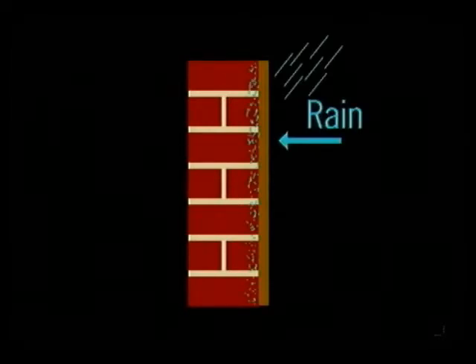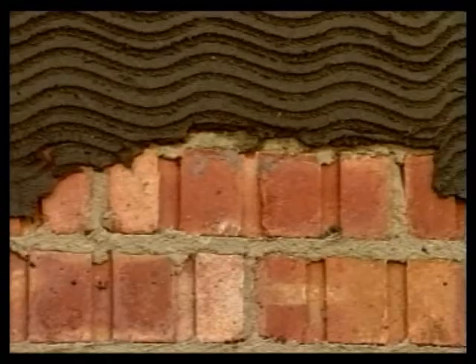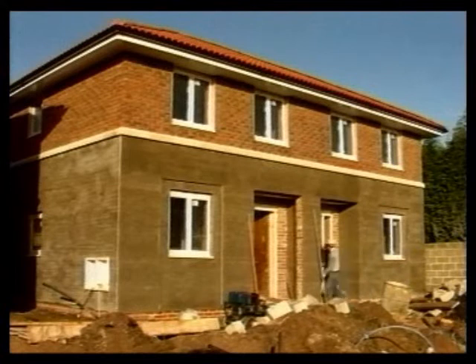Weaker mixes containing plasticizer or lime are less likely to shrink. In wet conditions, they will absorb some rainwater, but their relatively porous nature will allow speedy evaporation when the weather eventually changes. Weaker mixes are also more durable, as they can cope with stresses caused by thermal and moisture movement. These hard grooved bricks offer good resistance to drying shrinkage and also provide the right degree of absorption or suction to prevent the render drying too quickly. Dense concrete blocks have similar properties.